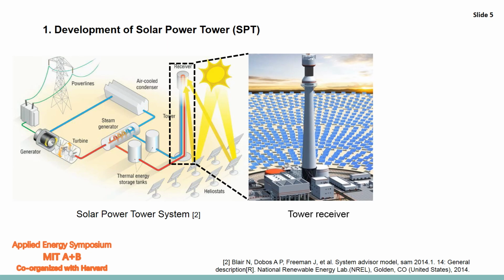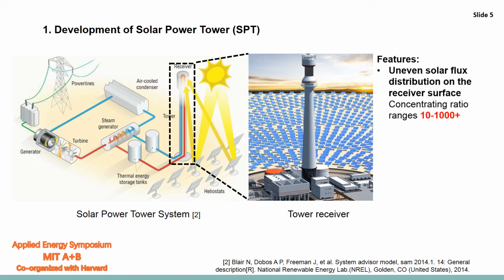The tower receiver is responsible for the solar energy absorption and conversion, so it is thereby the key component of the SPT system. For the tower receiver, it has two important features. The first is the uneven solar flux distribution on the receiver surface. A minimum concentrating ratio is only 10 at edge regions, but the maximum concentrating ratio reaches above 1000 at center regions. The second is its high temperature.